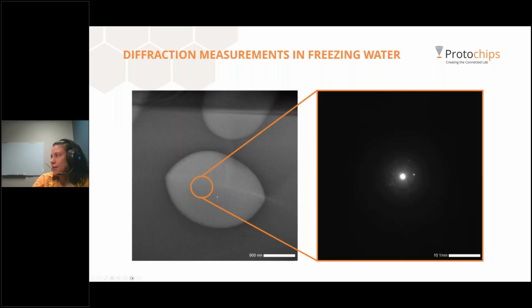I did do diffraction at one point. This is the image, the spot that I took the diffraction pattern from. I do see some spots indicating that there is crystallinity. I actually at first did it on the edge of the window and was seeing the crystal structure for silicon. Don't do that. This here is where we actually have some ice.